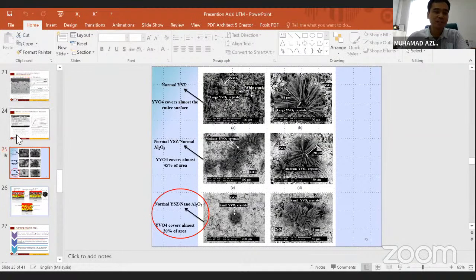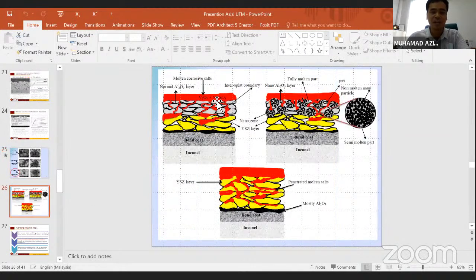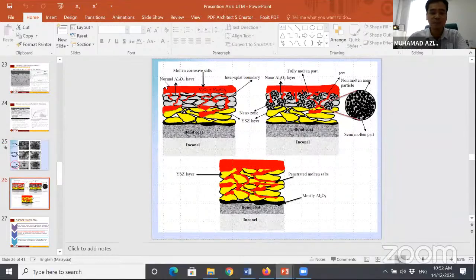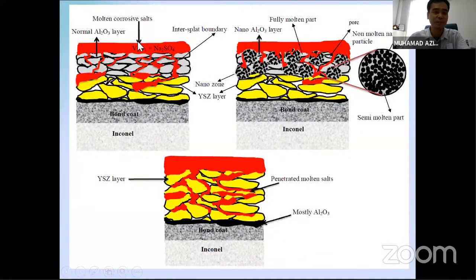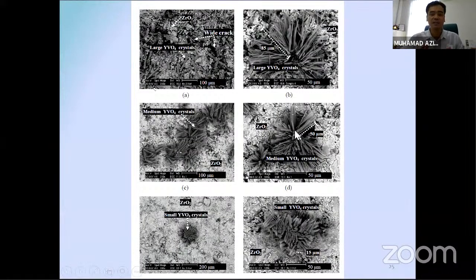When the corrosive salt attacks, you have vanadium pentoxide, and then sodium sulfate is the corrosive salt. When this corrosive salt attacks the substrate, the ceramic layer at high temperature, this vanadium oxide will react with the ceramic. So then we will lose the structure of the ceramic. How does it look? It actually looks like a flower. As a result of the vanadium pentoxide, we create flower-like detrimental oxide.